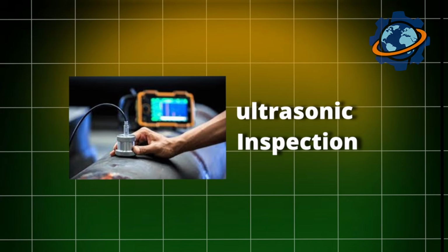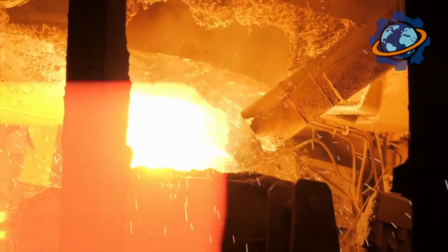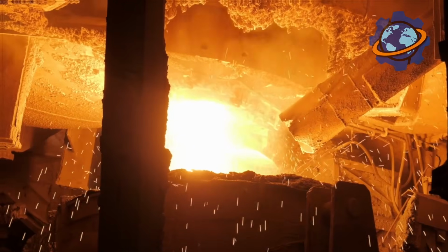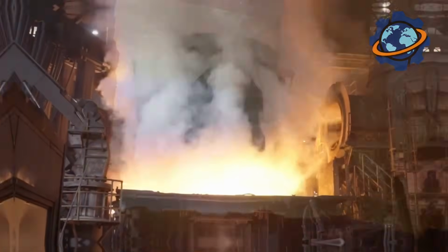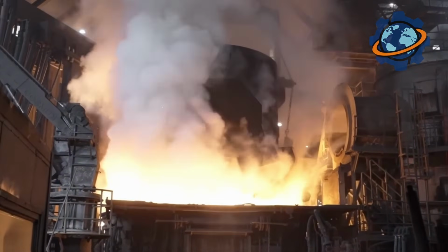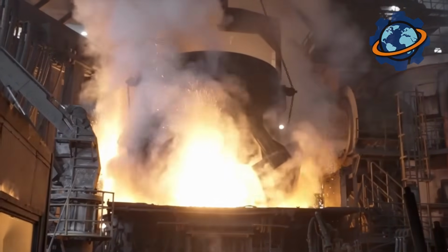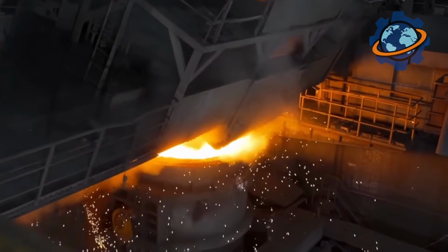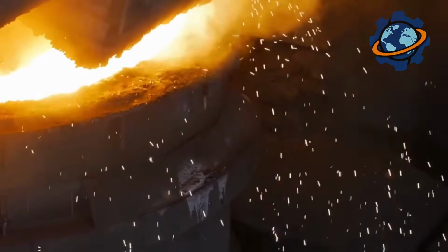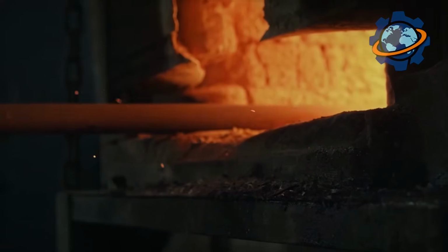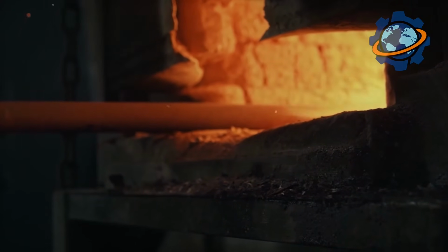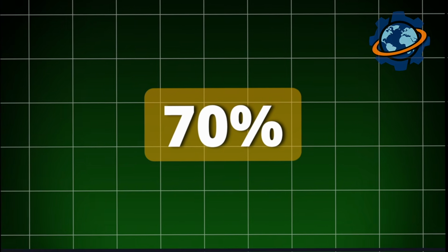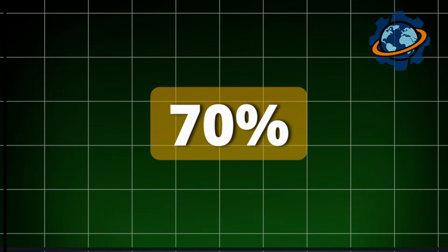That failure mode makes recycling challenging. You can't melt carbon fiber like aluminum. Heating destroys the crystalline structure that provides strength. Current recycling uses pyrolysis, heating composites to 1,000 degrees in oxygen-free environments, burning away resin while preserving fibers. Recovered fibers retain 70% of original strength, creating secondary markets. From plastic thread to aerospace revolution, the cycle completes.